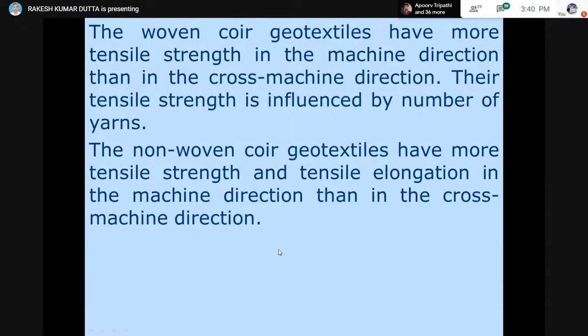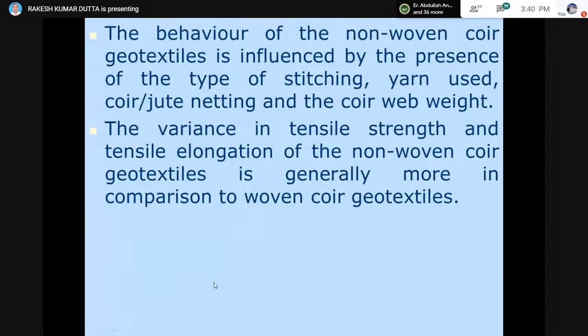The non-woven geotextile has more tensile strength and tensile elongation in the machine direction than in the cross machine direction. And the reason for this is that the stitching or the scrim is provided along the machine direction, not in the cross machine direction. We do the stitching in the machine direction only, and that is why we get more strength in the machine direction than in the cross machine direction.